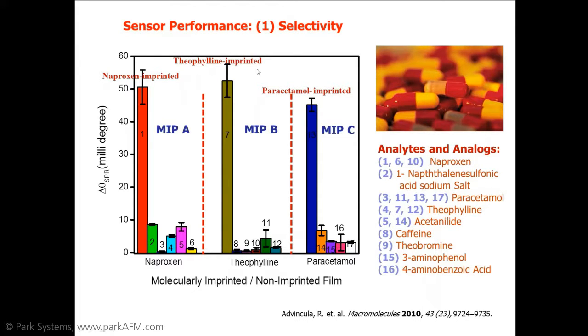If theophylline was imprinted, the rest of the analytes did not bind to it. And then finally, with paracetamol, the rest of the analytes did not bind to it. So what this tells you is that we can make custom-made or made-to-order films based on the original template that we use, achieving very high selectivity simply because the exact shape or cavity that's specific for the original analyte works very well and distinguishes it from the other analytes.